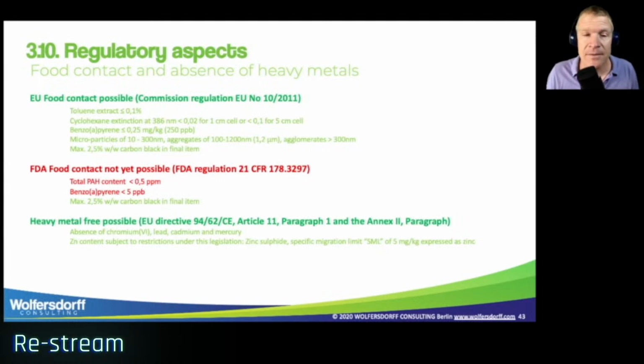However, zinc is subject to restrictions also under this legislation. And for the zinc sulfide, we need to make sure that the specific migration limit, SML, is lower than 5 milligram per kilogram, so 5 ppm expressed as zinc. So the zinc sulfide should not migrate out of our master batch or out of our plastic film or plastic product. Thank you very much.